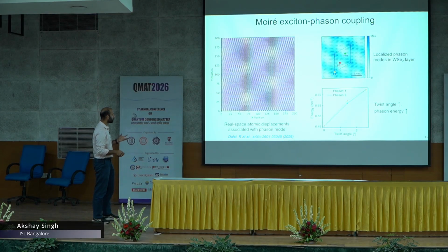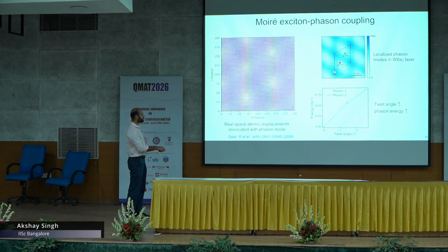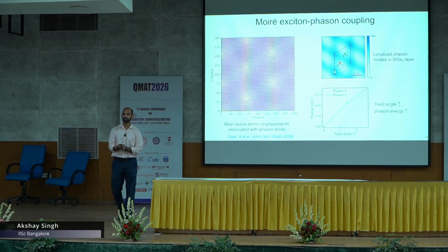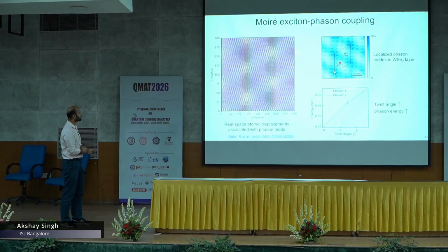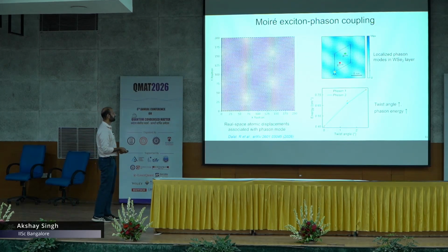And what's beautiful here is that with the twist angle, these phason modes actually increase in energy, which is what we are also seeing. So we think this is a very good explanation, and this is the first time anybody has looked at these exciton-phason couplings in a dynamical picture, right? So this is the first time anybody has done these kinds of measurements.